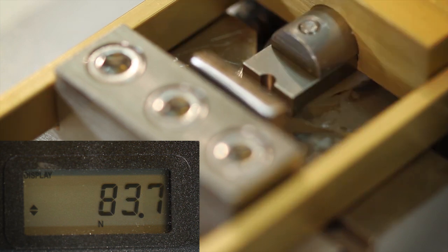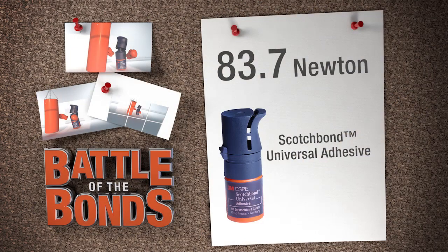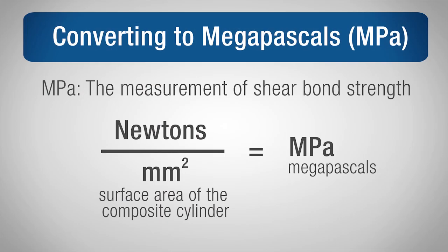In this example, 83.7 newton was the force needed to debond the composite using Scotchbond Universal Adhesive. The final step was to convert the newton measurement into megapascals, or MPa, which is the measurement of shear bond strength. To do that, the force, or newtons, was divided by the surface area of the composite cylinder, or mm squared. The resulting number equals the value in megapascals, or MPa.